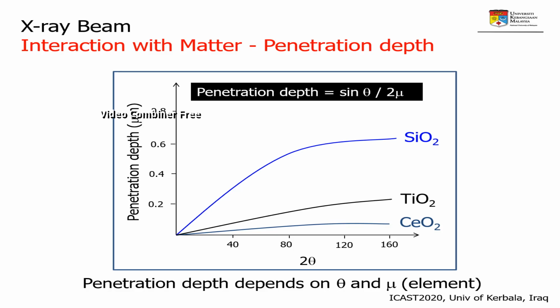This slide displays a graph showing the variation of penetration depth as a function of 2 theta for 3 different compounds, namely silica, titania, and ceria. As you can see, at high 2 theta values, the X-ray penetrates deeper into silica, but its penetration is limited to about 0.1 micrometer in ceria.